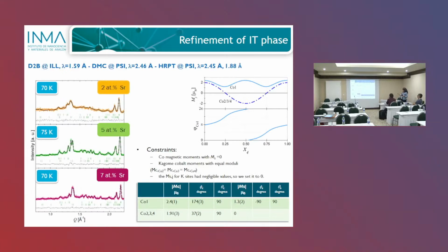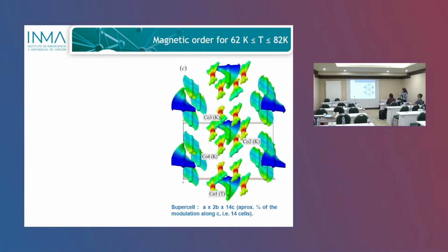And let me show you. This is the modulation of the magnetic moments at each site. And you will see that in the triangular sites, you have not only a modulation of the strength of the magnetic moments, but also a rotation, a helical rotation of the moments. And at the Kagome sites, you only have a modulation of the amplitude of these magnetic moments. So this is quite a complex structure, but it is not so surprising because of the strong frustration that this lattice presents.